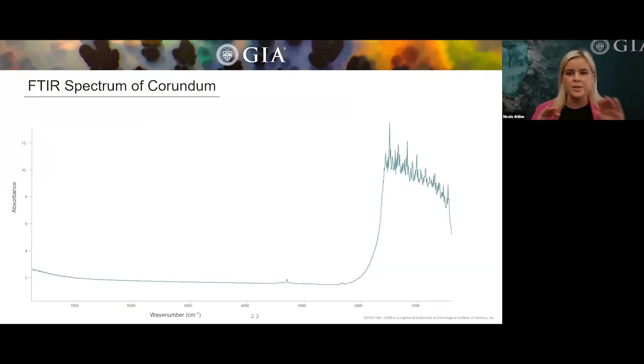So when we run a piece of corundum, this is a full FTIR spectrum, and you can see it's very big. We've got a couple bumps down there, but we're going to zoom in. When we run an IR for our corundum, we're only going to be looking at this area, that 2,000 to 3,800 centimeter area. This area of the spectrum is associated with hydrogen bonds within the corundum lattice. And we're going to be looking at these bonds because the presence or the absence of them sometimes tells us a lot of information regarding if this stone has seen heat treatment or not.